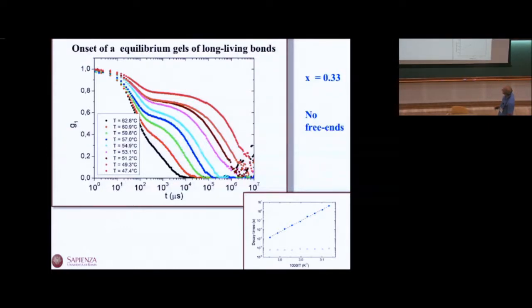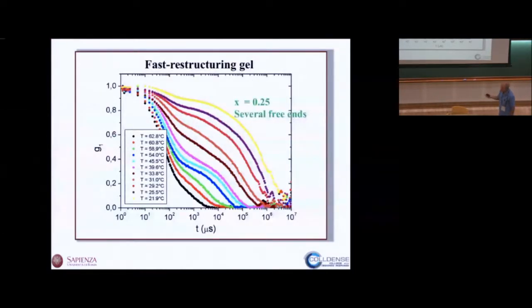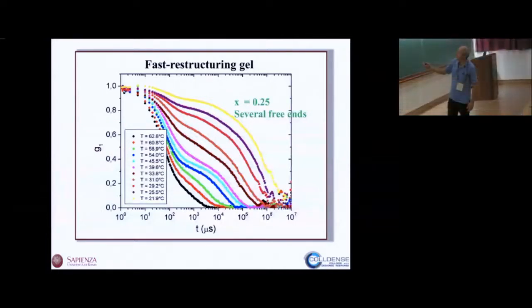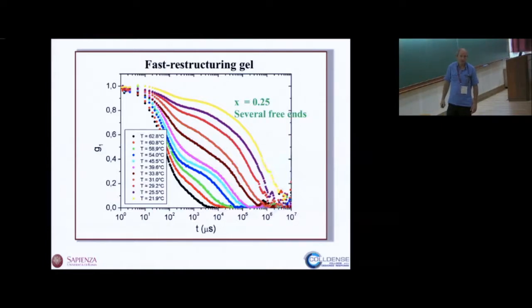So everything is clear. So no swap phenomenon. There is no speed up that we see in this one. Now let's look at the sample with the X25, in which we have seen that there are a lot of free ends. And now you see that even at 21 Celsius, this has not become as low as the previous one. So here there is really a significant speed up of the dynamics compared to the previous one. Let's look at the alpha relaxation time here.